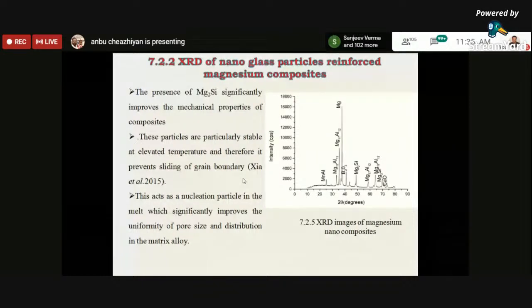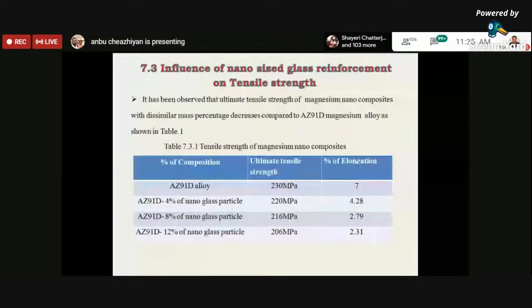And the presence of Mg2Si acts as a nucleation site in the melt with a significant alloy. So it's just nano hollow particles, so uniform pore size has to be maintained. And we go for the influence of nano-sized glass reinforcement on tensile strength. As per ASTM standard, it has been observed when the composite has been tested.